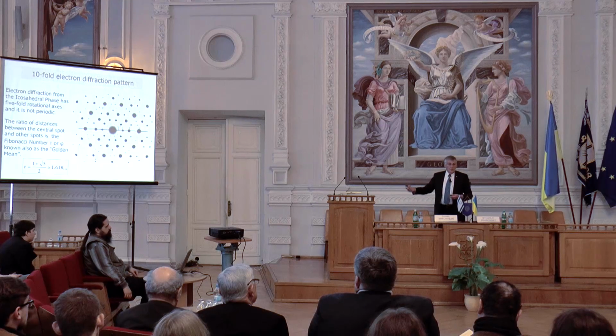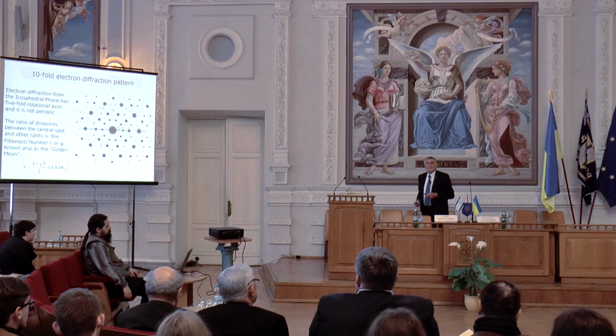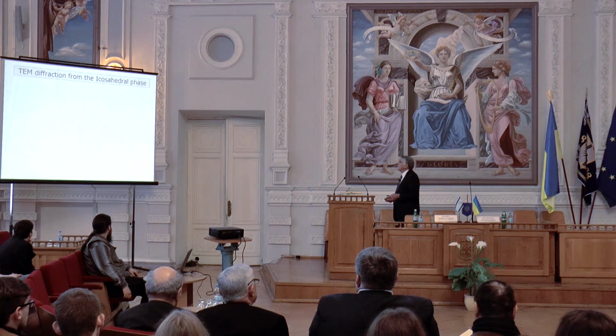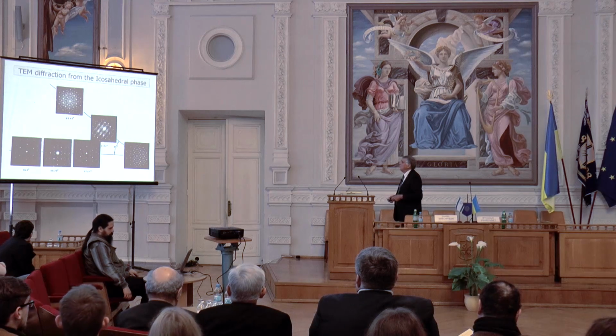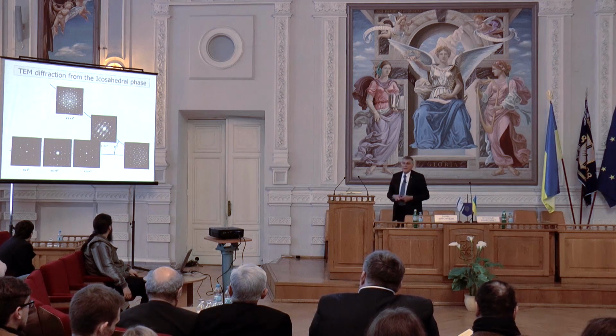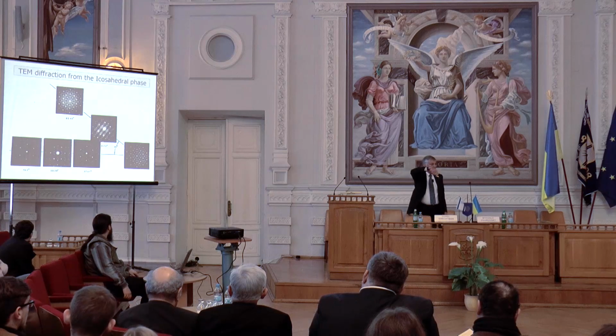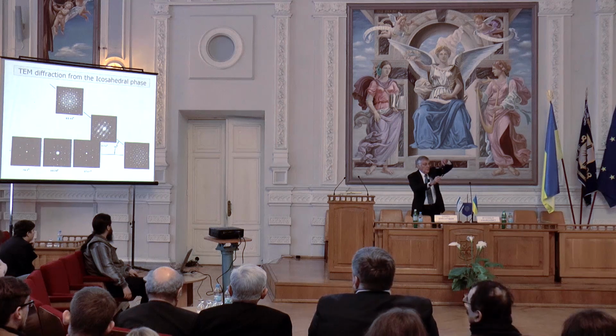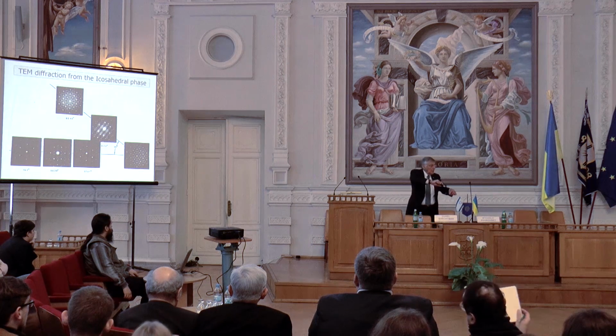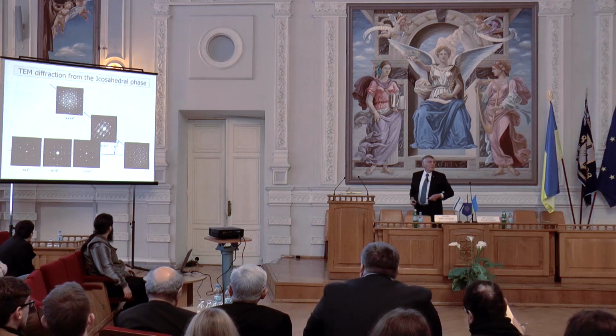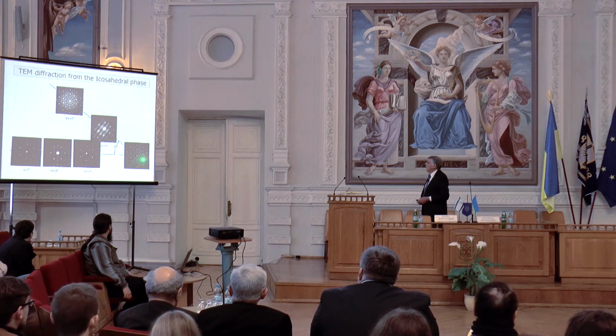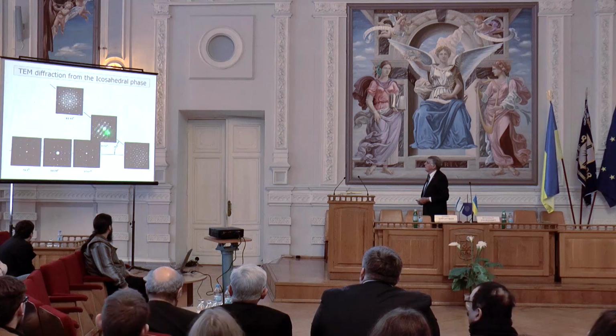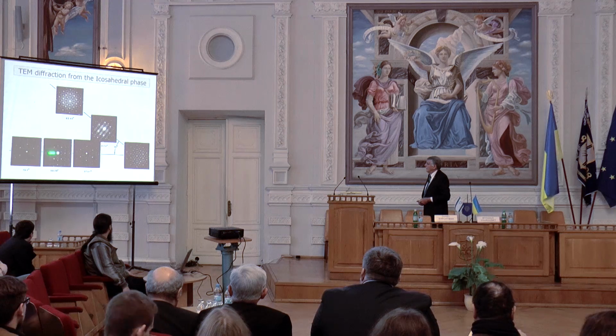What's going on? When I discovered this, I did not know what I had. I thought that I had a twinned structure. Now, before going into that, I'll show you other things. In the electron microscope, you can tilt your specimen and rotate it in a goniometer, so you can take a diffraction pattern from this position, this position, any position you want. So these are the main diffraction patterns that I have taken. Five-fold rotation symmetry here, two-fold here, five-fold again, and 5, 3, 2, 3 again.